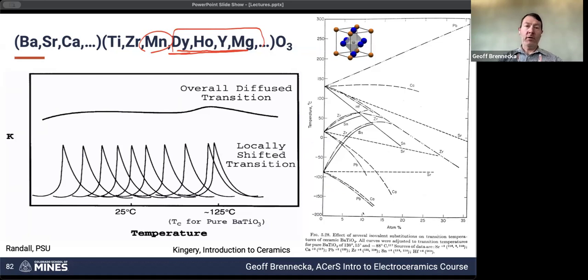So if you are making expensive enough capacitors that you can use platinum electrodes and people will buy them, then great. If you want to make them cheaper, you're probably going to have to use nickel electrodes or copper. And nickel and copper require a lower partial pressure of oxygen, so they don't oxidize, but that leads to increased oxygen vacancies in the barium titanate, so you can compensate for that with some of these. There are also multiple other aspects of it.